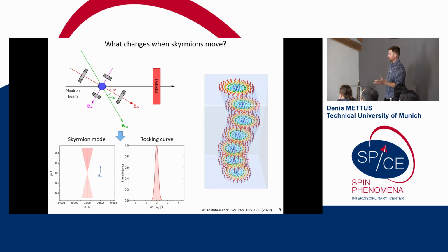So how do we measure moving skyrmions? In our experiment, we add some AC field so that, as a result, we have the total field tilting around the original direction by a few degrees. To show you how the curve would react, imagine that you have a skyrmion string looking up, something like this, but imagine it's straight, and imagine that it can instantly follow the field changes for a simple model.